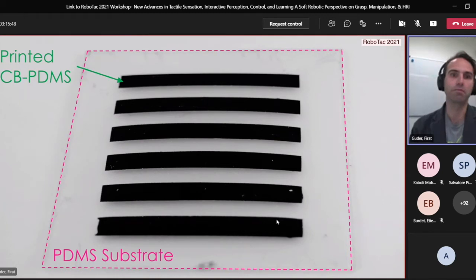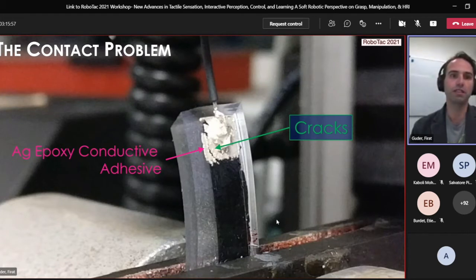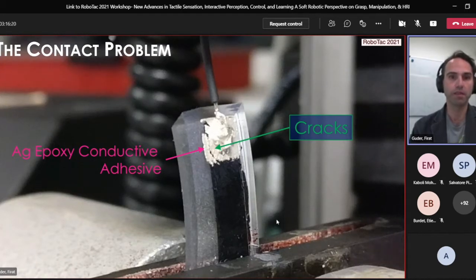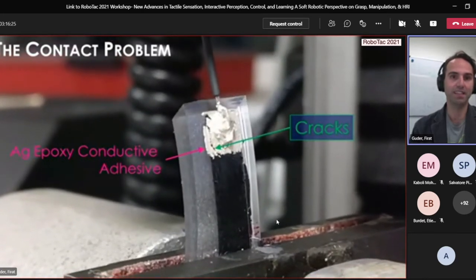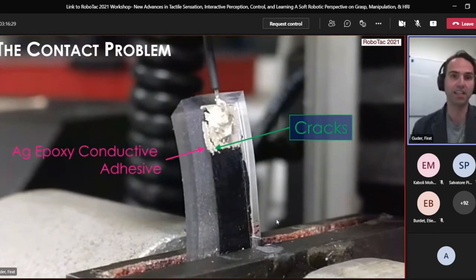And the reason why, again, we cannot see these materials out there is the problem with the contacts. What's commonly used in the literature, and I call this the contact problem, is people make these composite sensors and then attach the outside electronics with a silver epoxy conductive adhesive. The problem is that silicones are very inert, so they do not really react with the adhesive. And when we apply force, for example, in this case tension, we see that the adhesive starts cracking, and the electrical contact really breaks between the sensing layer and the outside electronics. And even if it doesn't break fully, sometimes the mechanical fragility of the adhesive basically adds a lot of error to the measurements, and we obviously do not want this if we want to use this as a sensor.